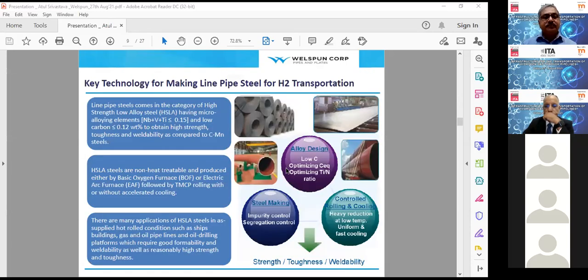Then I'll run through some critical parameters required to develop steel for 100% hydrogen transportation. This is based on the current specification and the data currently available, and as we are aware, a lot of research is going on across the globe to develop line pipe which is in compliance with the industry requirement. But fundamentally, the chemistry design should be with low carbon, a highly optimized carbon equivalent and PCM, and optimized titanium by nitrogen ratio. The steel should be as clean as possible with minimum segregation, and with heavy reduction at low temperature and uniform fast cooling. That is the essence of TMCP rolling, which most of the mills in the world can do right now.